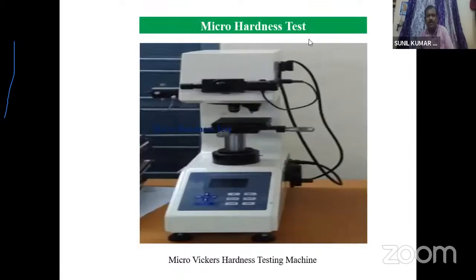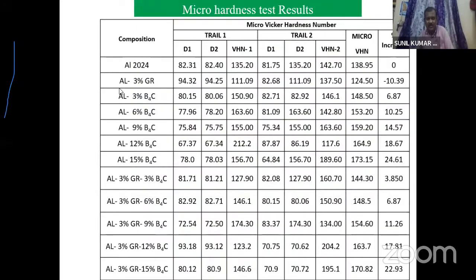Then coming to the micro hardness test. So this is the micro hardness test. For aluminum 2024, two directions are taken, so two values are taken for each and every specimen. Then the percentage of increase of hardness will indicate the percentage increase in hardness values. First of all, in trial 1, the micro Vickers hardness number is 135 for aluminum 2024. In the second case, 142. Then this is the total micro hardness value.